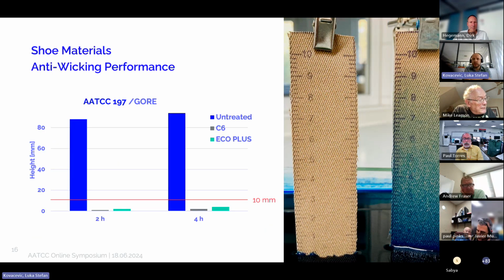The shoe industry has started looking quite late into fluorine-free water repellent products for various shoe materials. With shoe material applications, one of the most employed performance tests is the anti-wicking test or Gore test that you can see on the right-hand side. In this standard, treated fabric is immersed in aqueous blue solution, and the water must not rise above 10 millimeters within 2 or 4 hours. Again, you can see that our Eco Plus can achieve the same performance as a C6 finish. It has to be said, however, that to be comparable with a C6 finish, all the untreated material before finishing has to be free of residual surfactants.